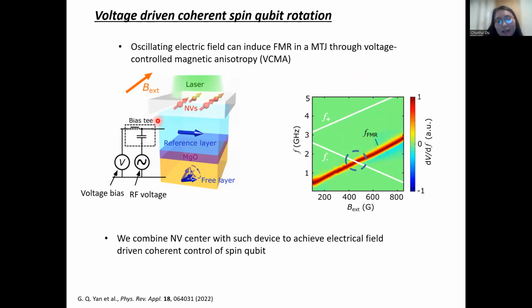So then we study the hybrid device properties. We can see that the ferromagnetic resonance of the magnetic tunnel junction crosses with the NV center frequency at 400 Gauss. So this is the frequency and the field environment where we can operate our quantum device. Then we monitor the spin state of the NV center by monitoring the photoluminescence as a function of the radio frequency voltage, so we can study the coupling between the NV center and the spintronic devices.